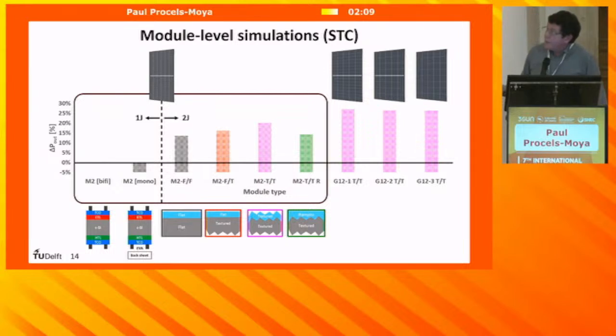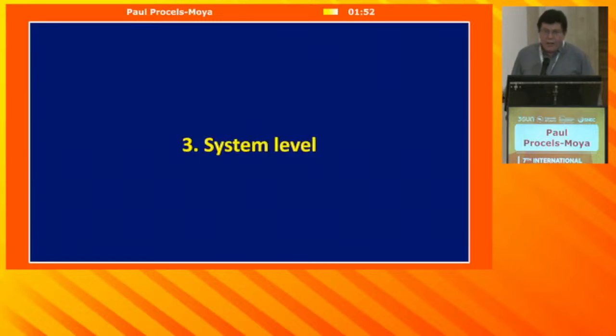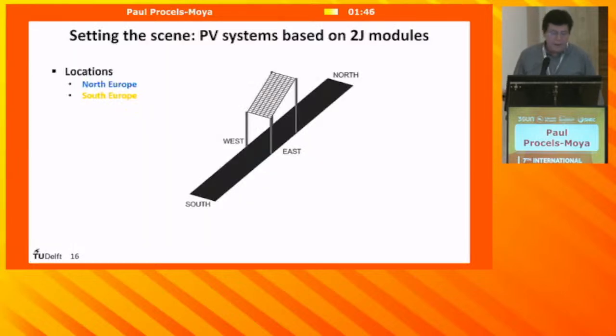So these are the main results, and there's a remarkable improvement in power output of the modules as compared to the monofacial module. It's a very high improvement. Now let's go to the system level. For that, we choose two different locations in Northern Europe and Southern Europe. We use a constant azimuth of south because both are in the Northern Hemisphere. Tilt, we use a constant value of 25 degrees. This is not the best one, but we use a standard for this comparison.